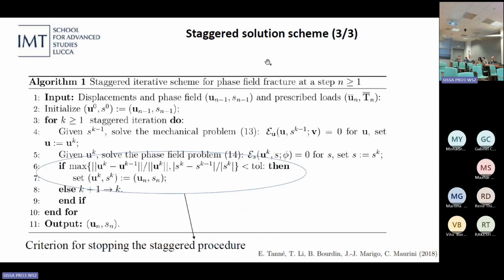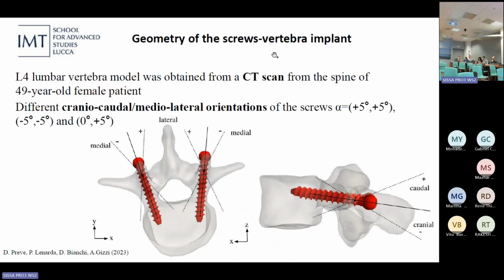Okay, so this is the staggered solution scheme that we adopted. First, we solve the mechanical problem where the phase field variable is frozen. Then we evaluate the displacements, plug them inside the phase field equation, and solve for S. We iterate those two until we reach convergence, and this is the stopping procedure to go to the next loading step. Okay, so going back to the modeling,